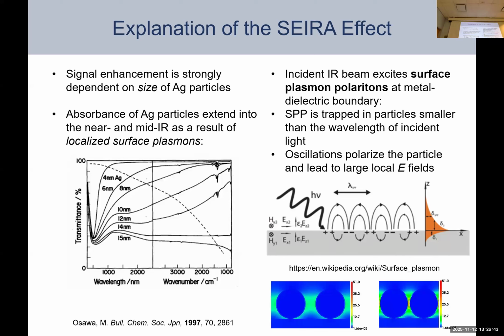So locally, in this nice picture from Wikipedia, as you bring two, let's say, high aspect ratio nanoparticles together, they can almost touch. Right in here, they kind of kiss each other a little bit. And in the middle, there's going to be a very high local electric field, which can really help polarize your adsorbed molecule. So we're essentially taking advantage of this very high local electric field to enhance the IR absorbance